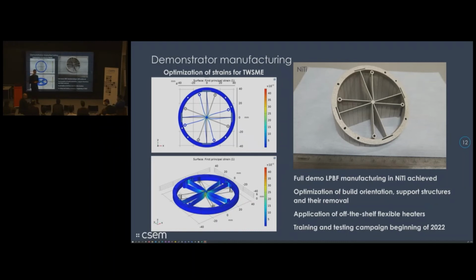When you do this 3D printing, defects in the material might be a topic to look at. I think you had also a slide in there. How does defect actually influence the mechanism of the whole structure? That's an excellent question. There are various defects that can be produced during LPBF. At this stage, the most important thing was to not have defects that would decrease the strength of the material, so we wouldn't be able to go to high enough strains to have sufficient strain recovery or one-way or two-way shape memory effect.